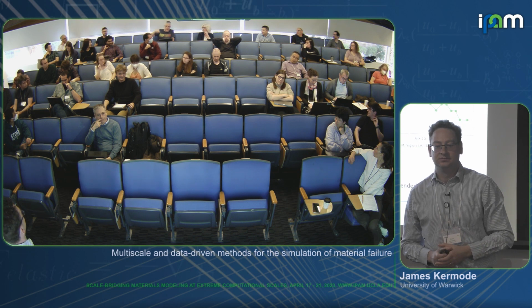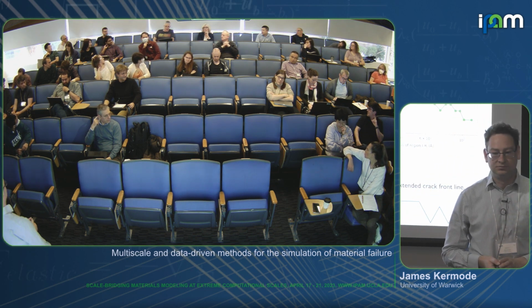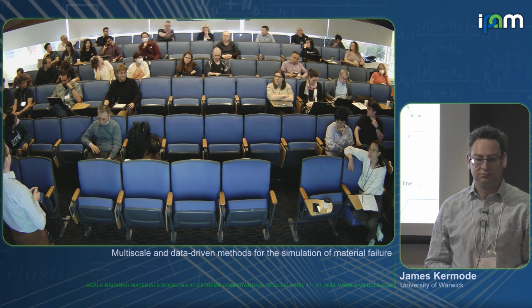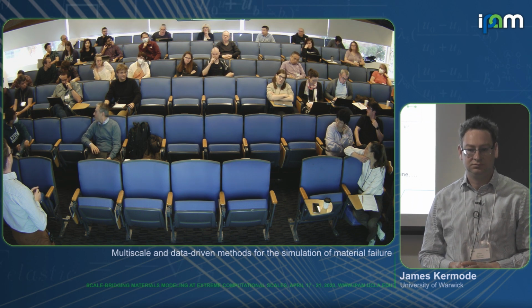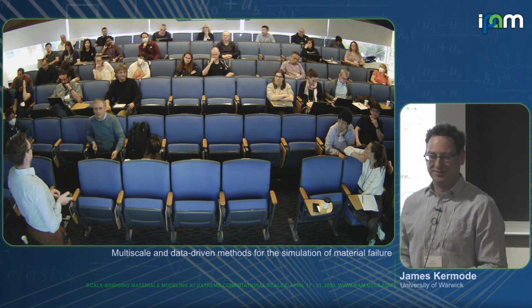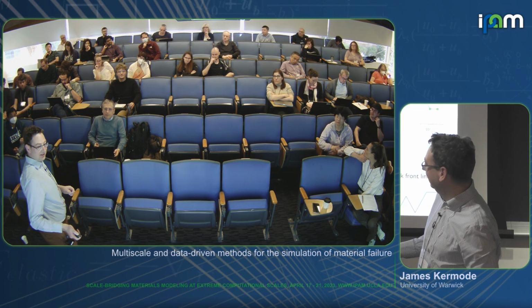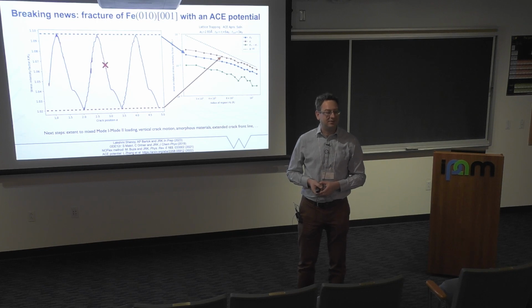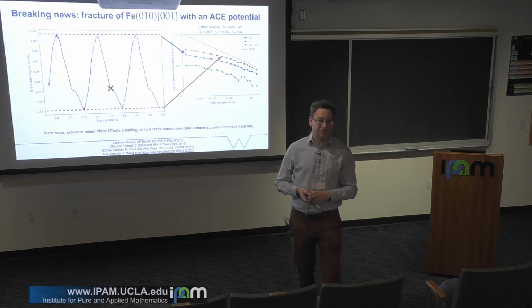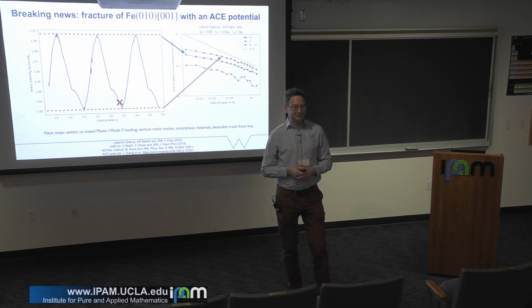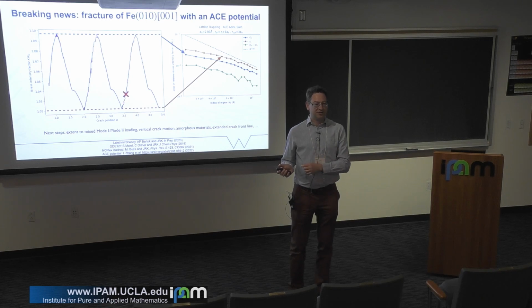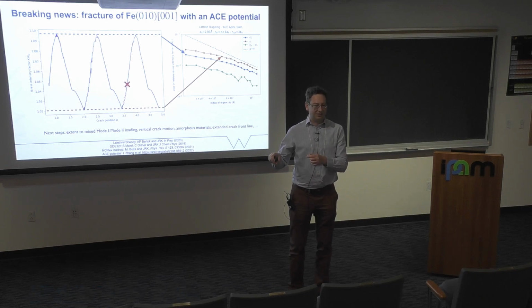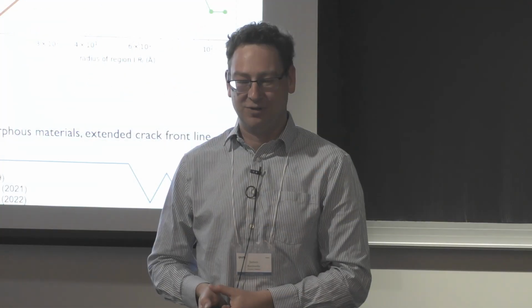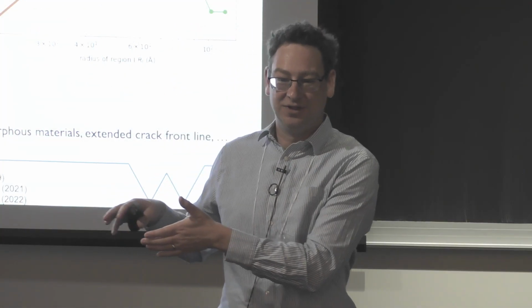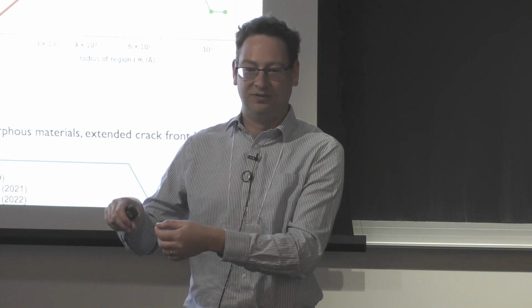So that's sort of the opposite question. I understand that things can be discontinuous and you go downhill, but I'm happy with a smooth path. No, it's not very smooth. That's because we're using quite big steps along the solution path. Are you sure the potential is smooth? No, not necessarily. The potential might not be completely smooth in this case. I'm also not correcting quite as well, so the tolerance on the optimizations that bring you back to the path is a bit looser in order to get this to work fast. The one I showed for silicon is super smooth, partly because the potential is smooth, but partly because I'm converging very well at every step.